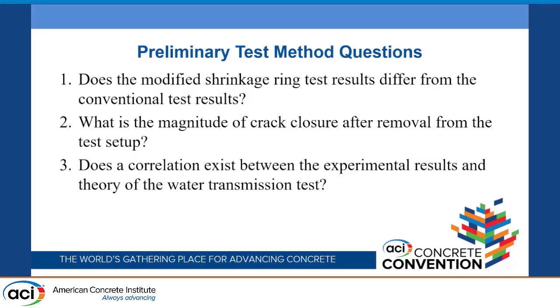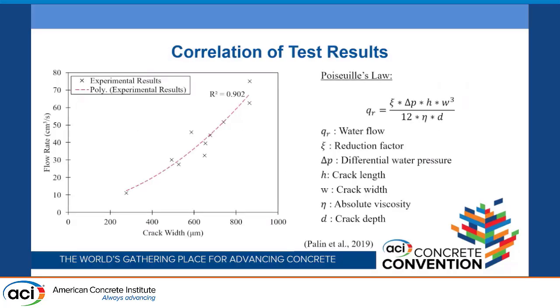Answering the last question first, doing a correlation of our test results, we had 10 existing shrinkage ring samples that were cast for a previous project. We measured their crack widths visually, and also measured them using the water transmission setup. We were able to get a pretty strong R-squared of 0.9, fitting with a polynomial trend, based on previous research on water transmission test setups using Poiseuille's law, where you're measuring essentially through two parallel surfaces, a crack.